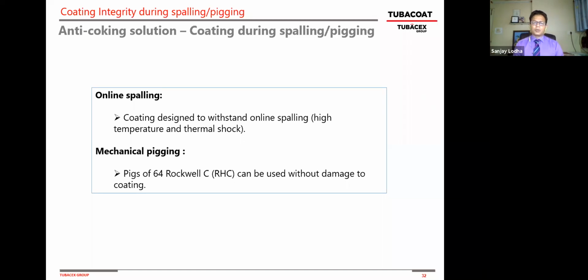And also remember, when we use these coated tubes, we're reducing a significant amount of inorganic contaminants, such as iron sulfide and the solid coke. So the mechanical pigging requirement is significantly lower, but also the material you have in the tube that's coking is significantly lower for the inorganic materials. That's another part. Next slide.